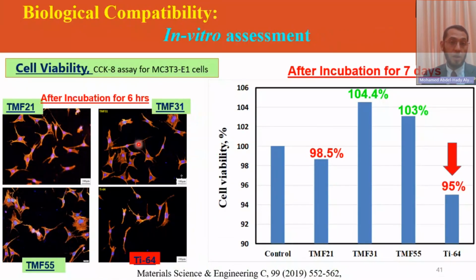And we can see here also the cells for some new low-cost alloys that we have developed, compared to the titanium 6-4. We can see after implantation, this is bone cell. After 6 hours, in only 6 hours, you can see the cells around on the surface of our alloys, compared to the cells on the surface of titanium 6-4. You see the cell here, the number is less. The cell itself is very thin. You know, it is a weak cell. So the cell is dying, but the cell over our alloys is very healthy. The number is increasing and so on.